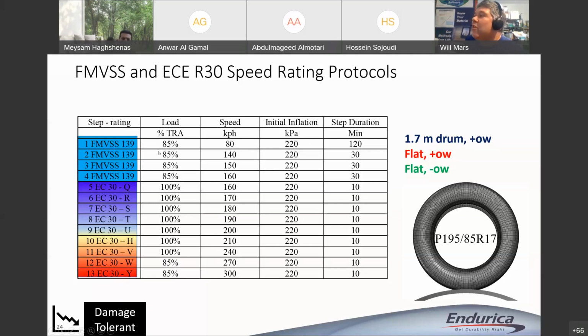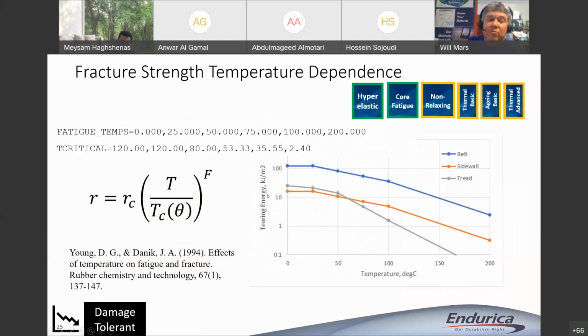And yes, to do that though, we're going to need to use an incremental analysis where we say, okay, run this load case for 120 minutes, and then run this load case for 30 minutes, and this load case for 30 minutes, and so on, up until the tire lets go, right? When the tire lets go, that basically gives you your letter grade for the speed rating. And we can simulate that. Now, in order to simulate this, you definitely need to take into account all sorts of things. You need to take into account temperature dependence, in particular, because at high speeds, the tire will heat up significantly. So we need to model that heat buildup.